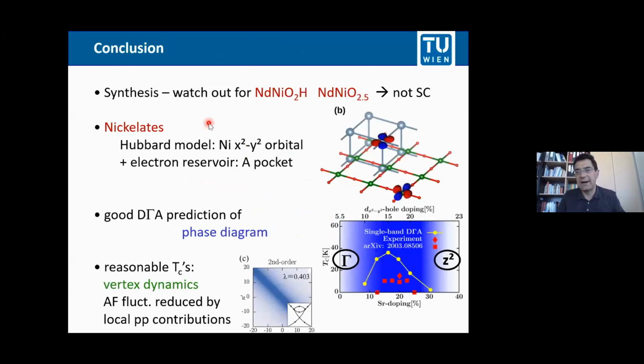Okay, here I come then to my conclusion. The first step regarding the synthesis: you have to watch out for extra hydrogen or extra oxygen. Extra oxygen is easy to detect in experiment. Hydrogen isn't. You're blind to that if you do standard experimental procedures. And that changes your electronic structure very much, and you won't get a superconductor. In particular, for low-doped systems, that is very relevant.